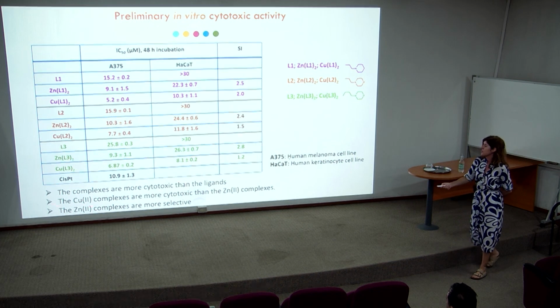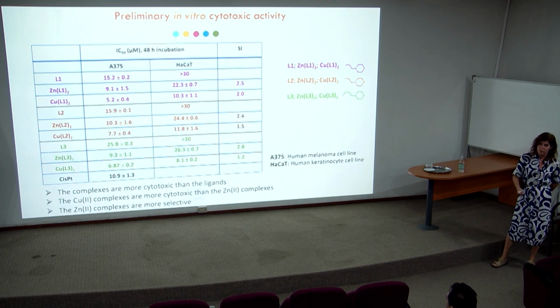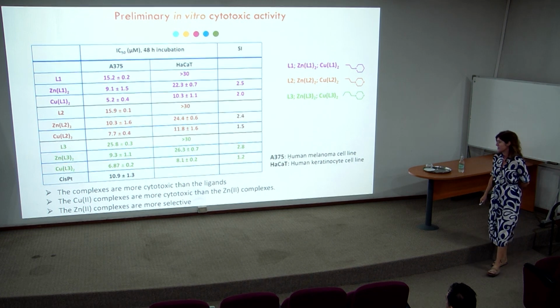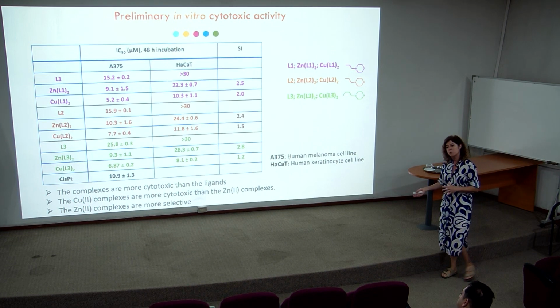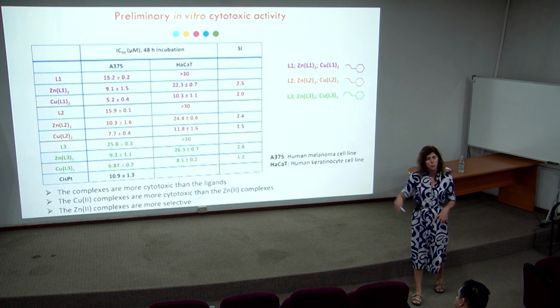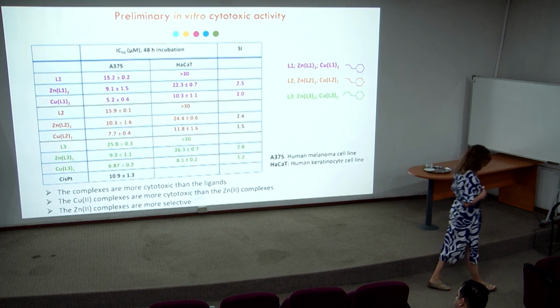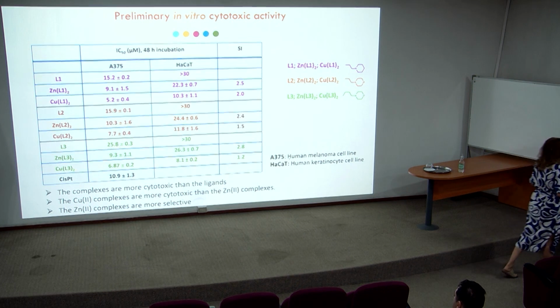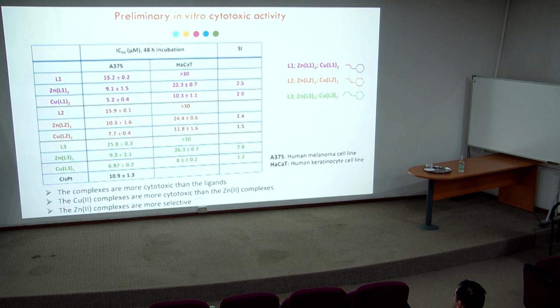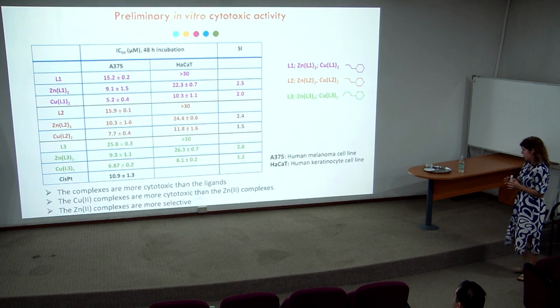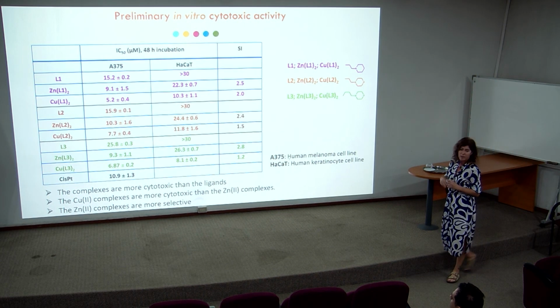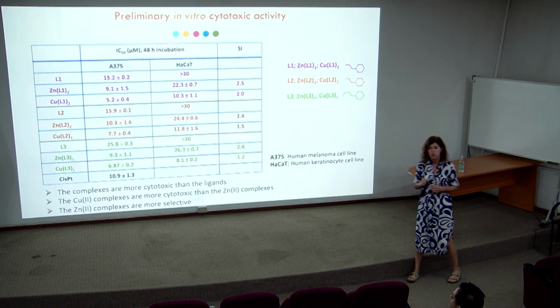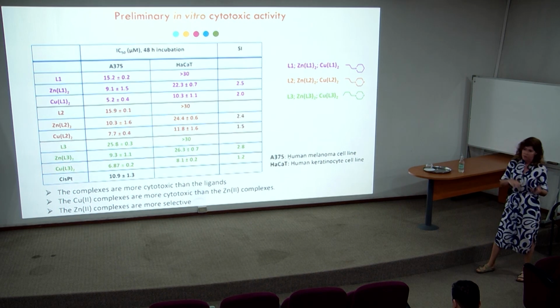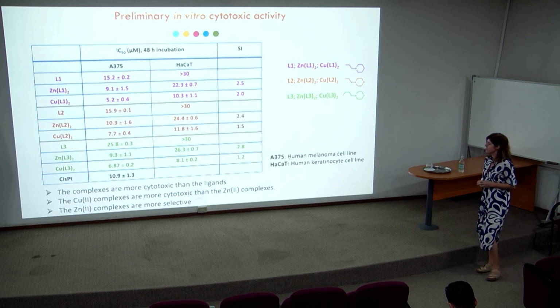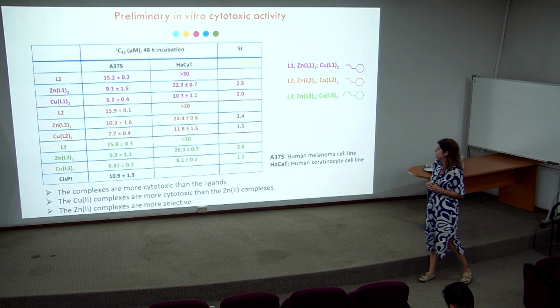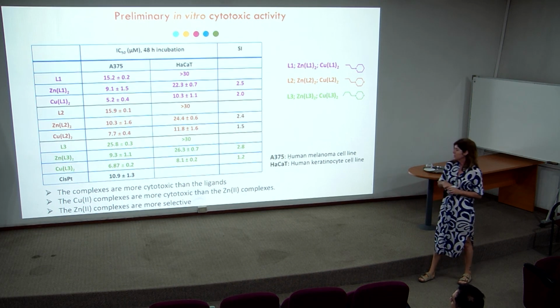And we could also observe that the copper complexes are slightly more cytotoxic than the zinc complexes. So right now what we are doing is we chose one of these copper complexes. We have been incorporating it in liposomes. The good result is that it still retains the cytotoxic activity, and so we are going to proceed to make a study which is quite similar to the one I showed you, although now it will be with melanoma and not with colon cancer. So we expect to have some exciting results from this system.